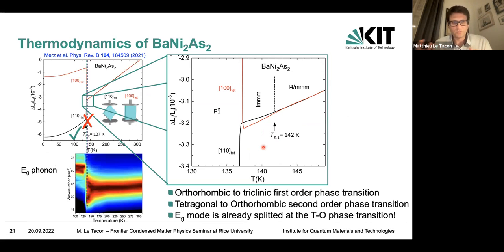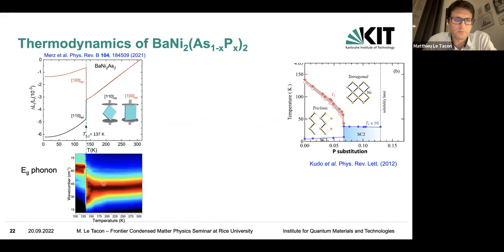I wanted to know exactly what was going on and how to compare this effect with the onset of the charge density wave, with the onset of the actual phase transition. So what was going on there? Clearly we nicely see the triclinic transition. It was well aligned with the thermodynamic measurement, but what we find is not only that the splitting was very large compared to this orthorhombic distortion, but clearly above the orthorhombic distortion, the splitting was already there. So the onset was much above that. And that was probably the most shocking part.